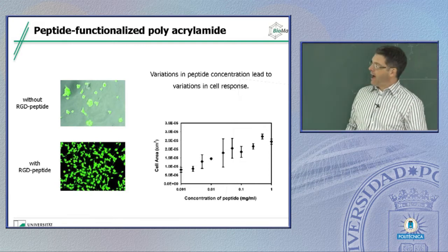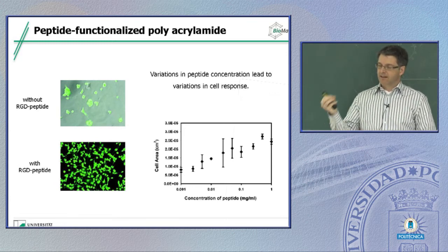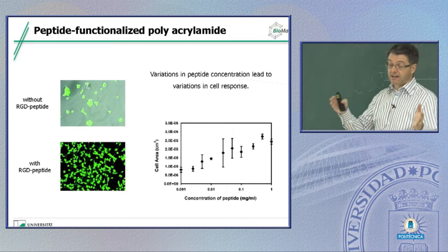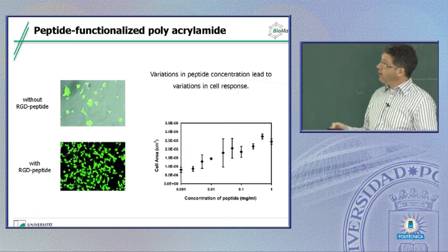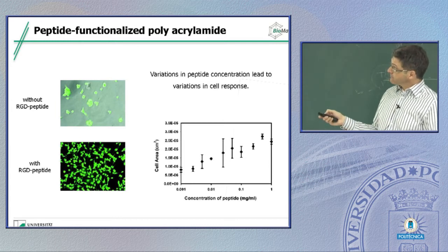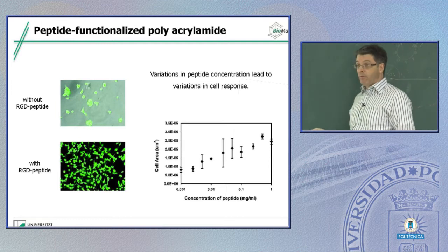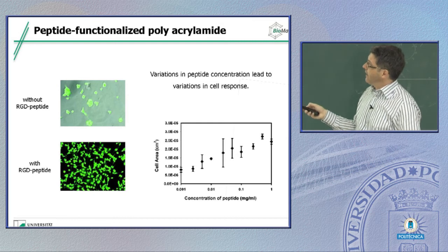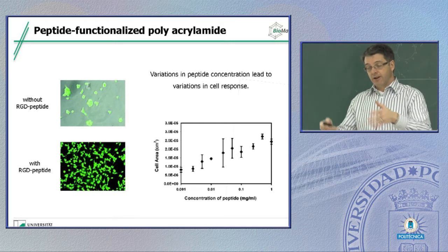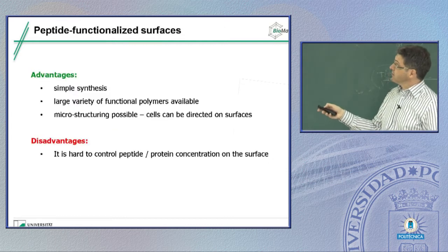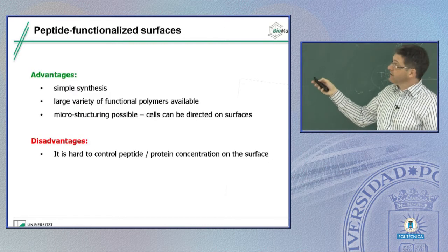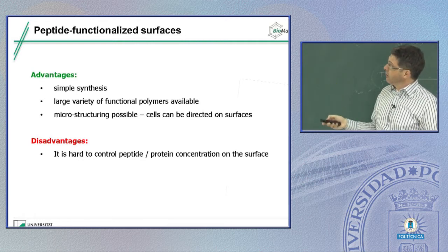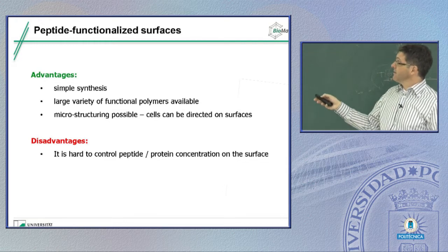So therefore, if you want to have cells attached to silk, you have to modify either the topography, but then this is again an unspecific cell attraction, or specifically by functionalizing it. And I showed you how we've done that with incorporation of cysteines. So we can incorporate a cysteine, and then we can actually label the cysteines. For instance, with the RGD peptides, we can do that in solution, and then make films, for instance. And then, of course, we have no control over the orientation, but you know, this is doable. But we also can first make a film, for instance, and then do the labeling.